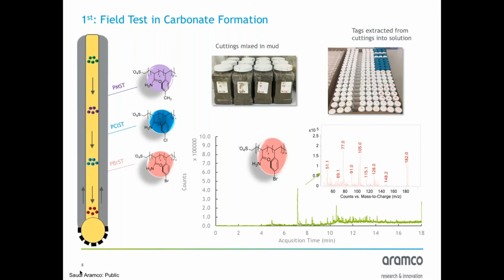Systematic differences were observed between depth estimated from the downward nanotag travel time versus the conventional method that the mud loggers are using. And the results actually showed a clear example of unintentional borehole enlargement, that is a systematic error that the nanotags technology can correct for. The pyrolysis GC mass detection of the nanoparticle is especially beneficial for the unconventional reservoirs that need to use cuttings to determine total organic carbon, kerogen, bitumen content, as well as the maturity at a precise depth.